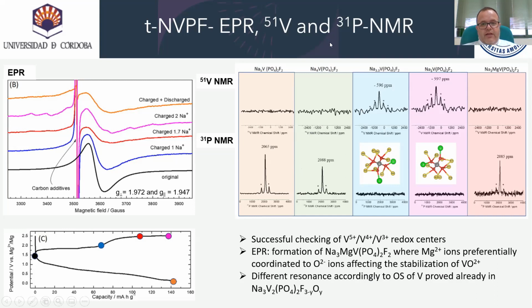After partial and total charge, the 51 vanadium spectra exhibit clear signals at minus 596 and minus 597 ppm with their corresponding spinning sidebands, respectively. The signals are located in the region ascribable to vanadium 5+. Mentioning the composition in the upper part is worthy because this composition is after the electrochemical reaction. We confirm the oxidation state. The 31 phosphorus NMR spectra is also provided here.